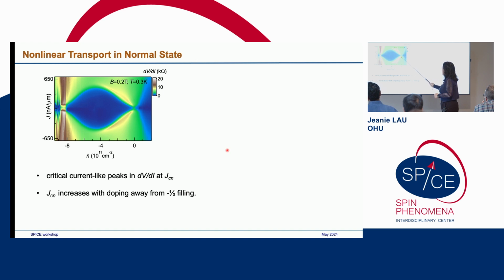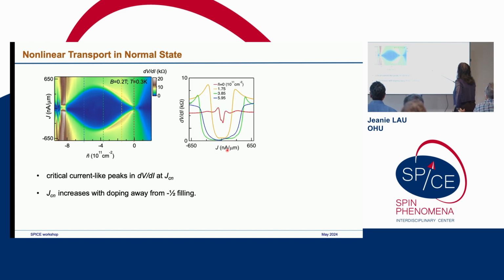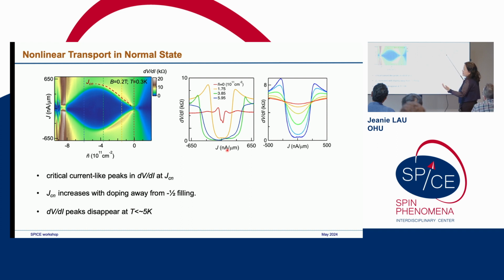What's interesting is that it looks like a mouth with lipstick, which looks pretty weird. This lipstick shape corresponds to peaks in the differential resistance. At small bias there is a low but finite resistance, since this is a normal state, and then the resistance increases sharply to reach a peak before it disappears. This peak goes away roughly linearly from the half filling point. If I raise the temperature, this is the 5 Kelvin data, then the peaks disappear.